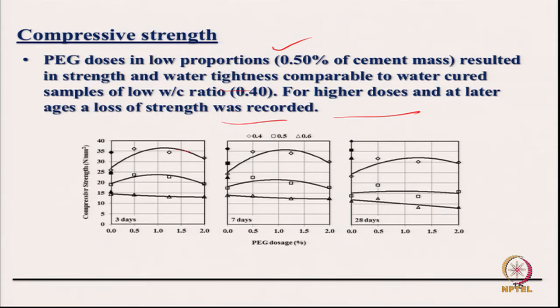So, you can see that strength increases and there is a reduction, for different water cement ratios we are talking about. Of course, this is 7 days, this is 3 days. So, this is PEG doses, different water cement ratio. This is high water cement ratio. In high water cement ratio, there is no problem. In the lower water cement ratio, this reduction is observed. So, you can use them, but after proper verification.